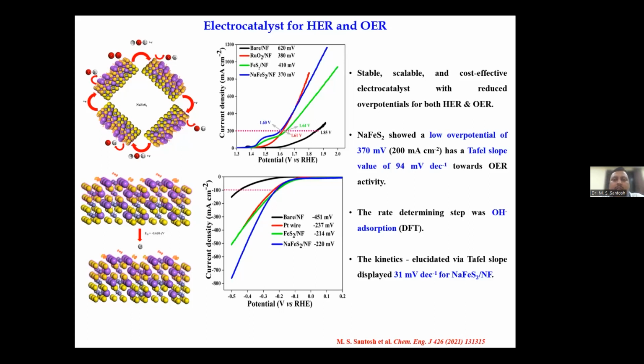Fortunately, we were successful in synthesizing the material effectively, and we initially started with testing this material for the effectiveness in terms of photocatalytic degradation of pollutants. When we observed significant degradation abilities of this material, we wanted to expand its application to electrocatalysis and study how good the material is in terms of producing hydrogen or enabling hydrogen production.